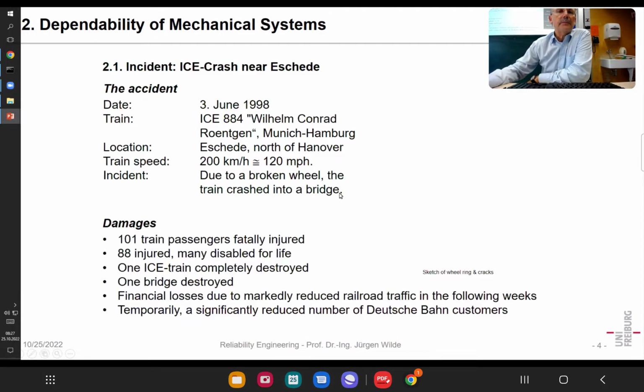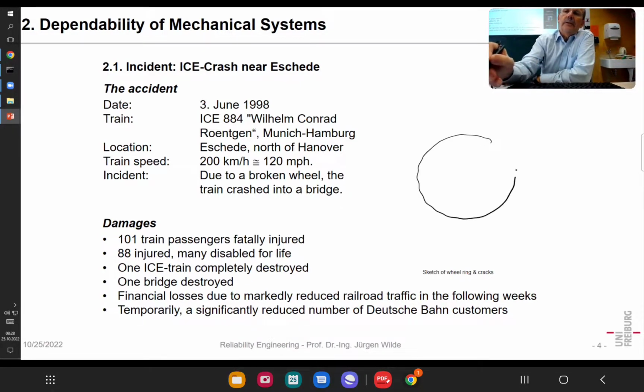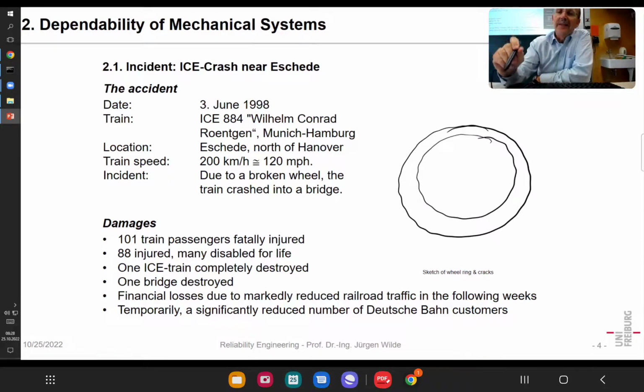But now let's have a more detailed description. So that was 1998, an ICE. It was ICE first generation. It had a speed of roughly 200 kilometers per hour. And what it had was a broken wheel. That wheel was, let's say, a two-part construction. That's a railroad wheel. Maybe it's more round than here. On the other hand, also a wheel gets some kind of wavy on the surface, so it gets some ripples. Also, the rail gets some ripples, and so from time to time it's turned down to make it smooth again. Otherwise, the ripples lead to much noise and discomfort.